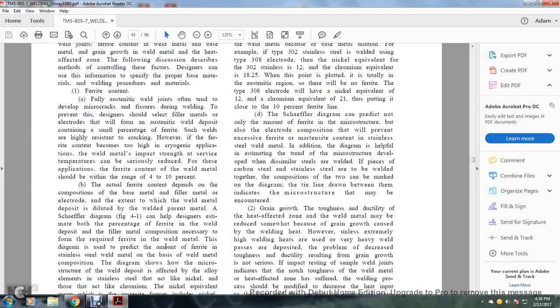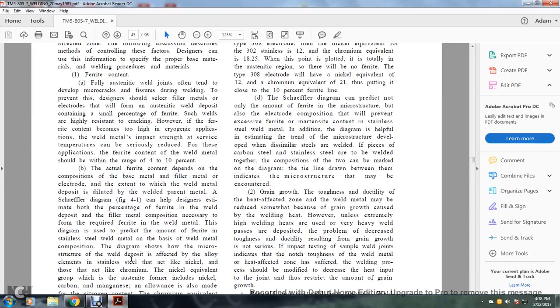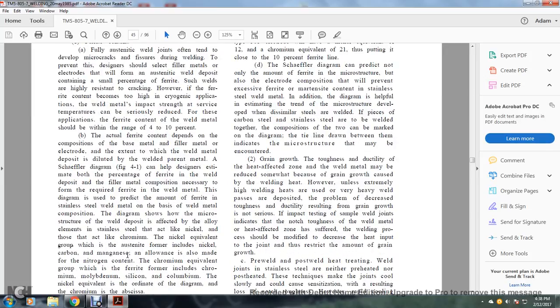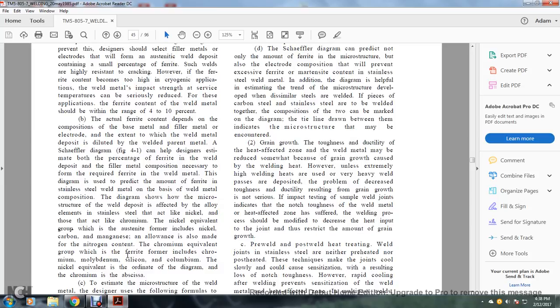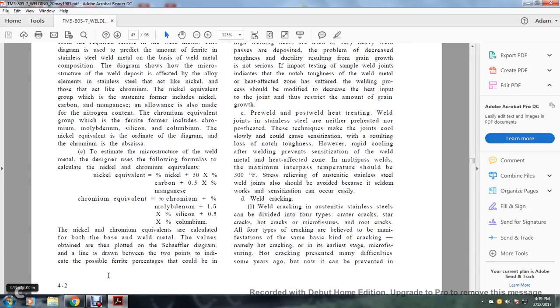The diagram is used to predict the amount of ferrite in the stainless steel weld metal on the basis of its composition. The diagram shows how the microstructure of the weld deposit is affected by alloying elements in stainless steel that act like nickel or like chromium. The nickel equivalent group, the austenite formers, includes nickel, carbon, manganese, and also nitrogen content. The chromium equivalent is the group of ferrite formers and includes chromium, molybdenum, silicon, and columbium. Nickel equivalent is the ordinate on the diagram, and chromium equivalent is the abscissa.